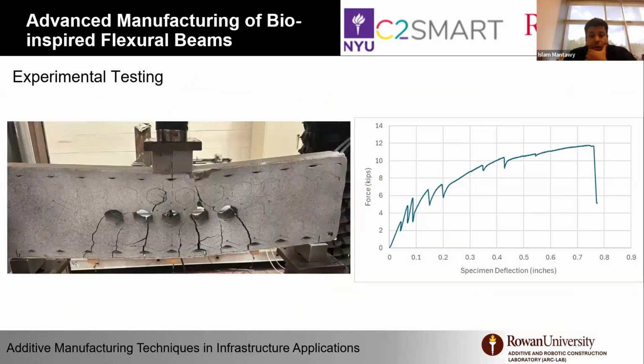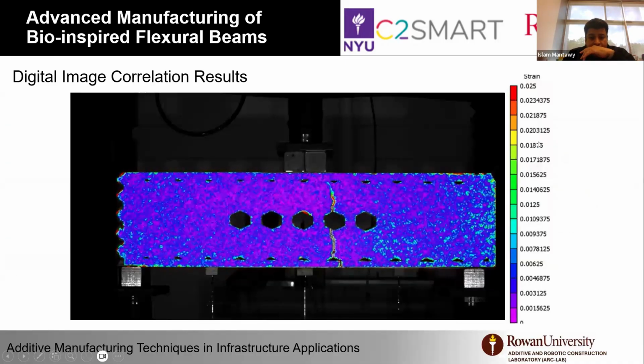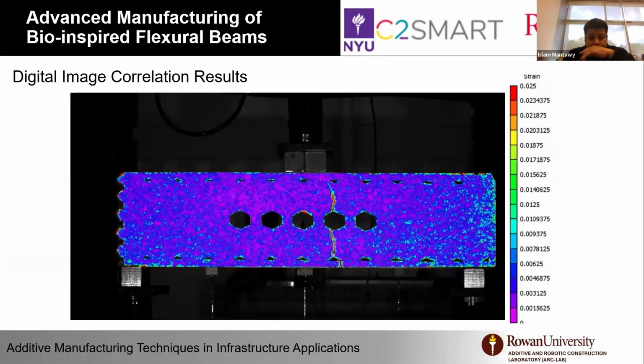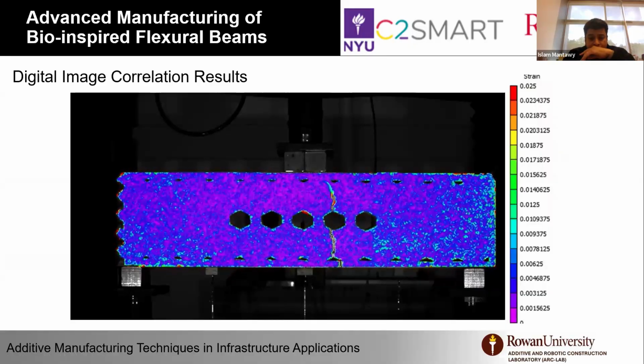And you can see here, because the cable we use is kind of flexible, when it cracks, it takes time to re-engage. It's not fully bonded the way rigid reinforcement is bonded. So we usually have drops in the capacity, but it always keeps going up until yielding of the strand itself. And here is one example of the test that we did at Lehigh University, where we did digital image correlation on those beams.